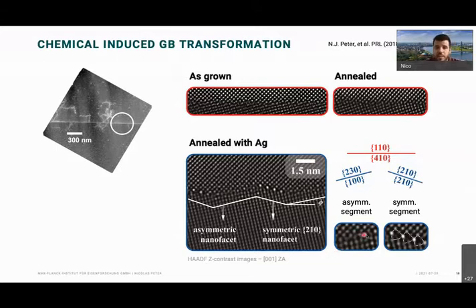The asymmetric segment is a little bit more confusing. It's not so clear how exactly the atomic structure looks like. This is related to, at the grain boundary, atoms become fairly mobile under the conditions we chose in the STEM. Anyways, it's just a really complex structure, how it's supposed to be for an asymmetric boundary. And the planes can be seen here, so it changes from a 110, 410 boundary into a faceted 230, 100 boundary and the symmetric 210 boundary.